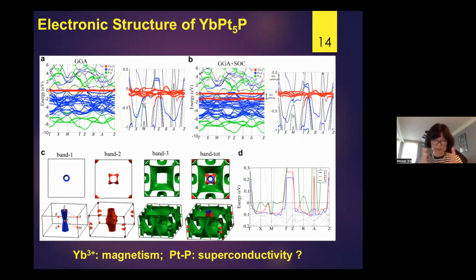And then we tried to think if this is a heavy fermion system. However, we studied the band structure and we calculated the bands. In this band structure, we didn't see ytterbium contribute to the superconductivity. So it could be a conventional superconductor. It's not a magnetic-mediated superconductor. So it's different from the heavy fermion.